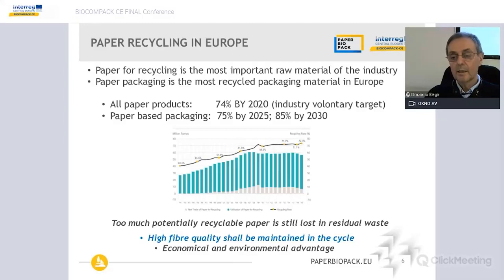The other reason is that the more we increase the recycling rate, the more we have to recycle also those products that are difficult to recycle. And this poses, of course, some constraints and some problems for the recycling process. Nevertheless, especially if we want to get by 2030 up to this 85% for packaging, we have to understand that we need to recycle also those products that are not so easy to recycle. And actually, one of the issues is to maintain also the high quality of the fiber that shall be maintained in the cycle, and this would be both an economical and an environmental advantage,